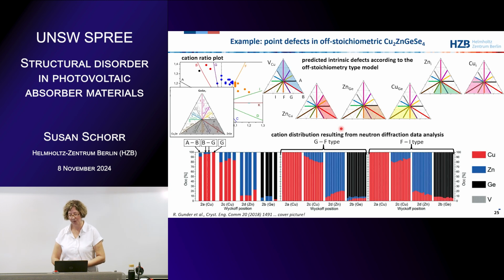Okay, this is just one overview. This is the cation distribution, which resulted from our neutron scattering length analysis. We start with this AB type sample going to BG, G, and then GF type and FI type. You see very nicely here the copper zinc disorder between the 2c and 2d position, also here between the 2c and 2d position, and also here. So regardless of which off-stoichiometry type you have and which point defects you can see, for instance, here copper on germanium, you always have copper zinc disorder.